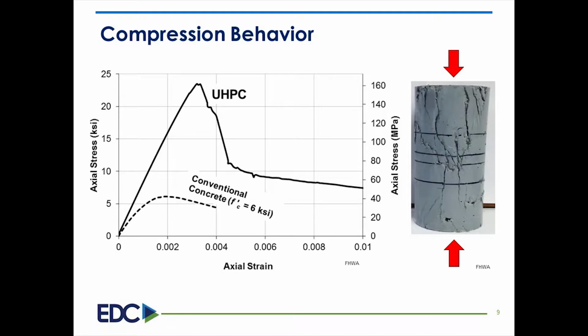As we see here, the strain response to stress, it's twice as stiff as the conventional concrete, and it's about 3 to 4 times stronger than conventional concrete. And even though this strength is very important, it's not as important as the tensile characteristics of the ultra-high performance concrete, which we'll look at next.